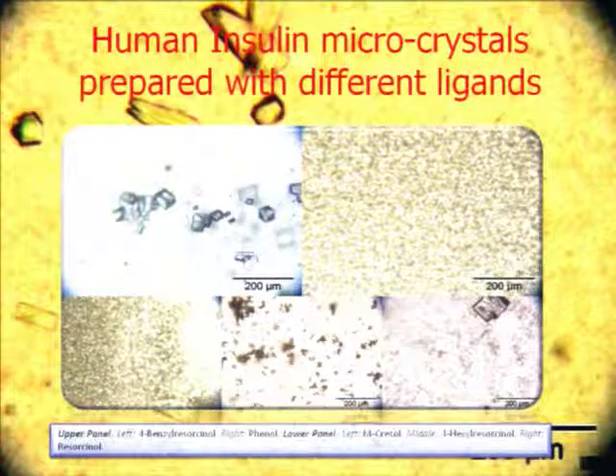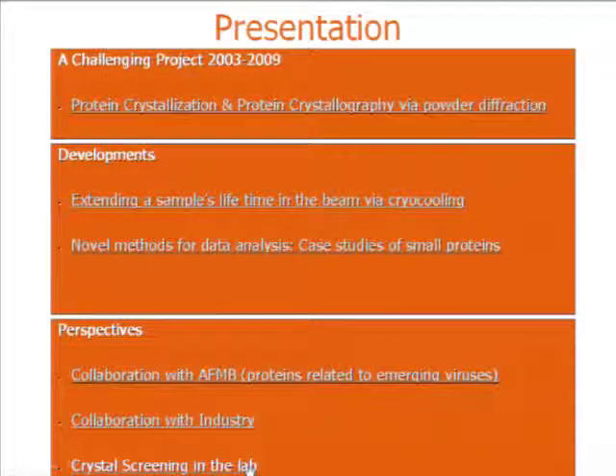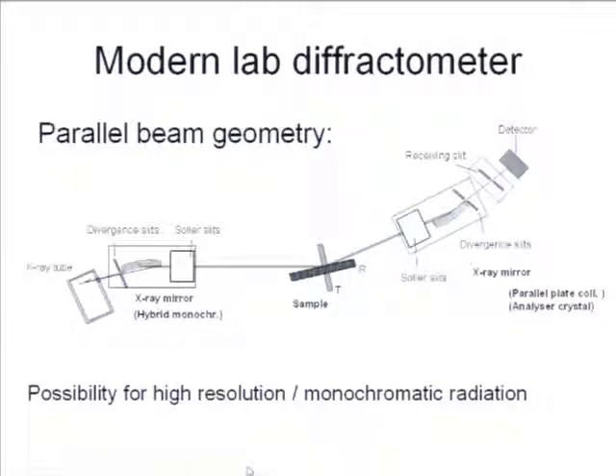These are samples that my three Greek students prepared using different ligands, benzyl, resorcinol, phenol, cresol, and so on. And these are the samples we got to Grenoble with 150 samples, 4 people working day and night. It's a huge production when one has students. So I can already say that we have found another new polymorph crystallized at very low pH, but I'm not ready to present it. Hopefully in Madrid we will have more results to show. And finally, I'm trying to set up a lab in Greece, apart from our crystallization lab, which is ready and operational, a diffraction lab where we can screen these 150, 200 samples and go to Grenoble with the best ones.